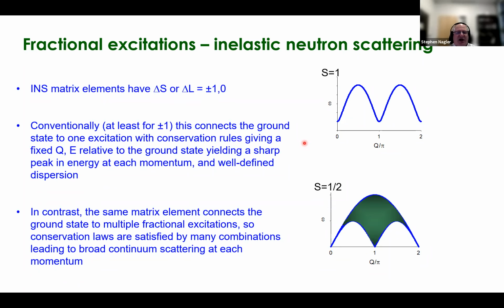So if I have a simple situation with an ordered ground state, and I think of what makes a regular magnon, which is a spin flip, a delta S equals plus or minus 1 type matrix element, I'll get one excitation, and conservation rules mean that there'll be a fixed momentum and energy relative to the ground state. So I tend to get something that looks like this. I get a sharp peak as a function of Q, and I have a well-defined dispersion relation.